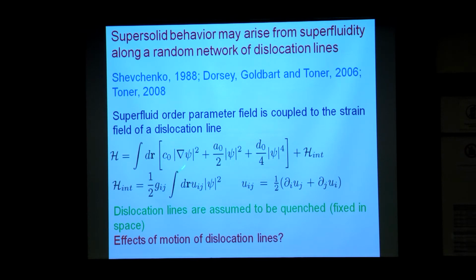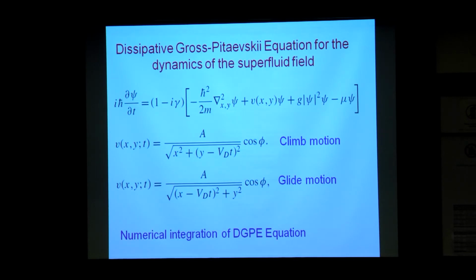And here the claim is that near a dislocation line, there is a coupling of the strain field of a dislocation to the superfluid order parameter, and as a result one could have superfluidity occurring near the core of a dislocation line. The question is, what happens when the dislocation line moves? To understand that, this student, Oriel, did a small calculation, which is basically this Gross-Pitaevskii equation, where again you use the same coupling, this V_xy. This is the coupling between the dislocation line and the superfluid field.